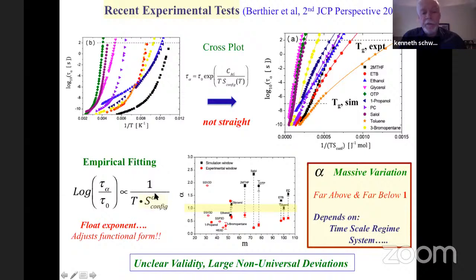But remember, floating the exponent is changing the entire temperature dependence of this function. So you can more or less straighten this data by changing the exponent, and then you can ask, what do you need to do? So here's the plot from the paper. What the exponent is, Adam-Gibbs and the elementary RFOT would be 1, but the alpha is massively variable. It depends on whether you are analyzing in the simulation window, that's the black points. It depends on whether you're analyzing in the experimental window, that's the red points. It depends on the system. The exponent can be much larger than 1 or much less than 1. So this is very worrisome to me, and what you want to conclude out of this is up to you, but speaking for myself, I find this troublesome with regards to the configurational entropy scenario.